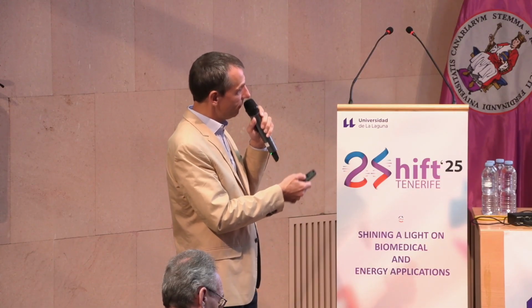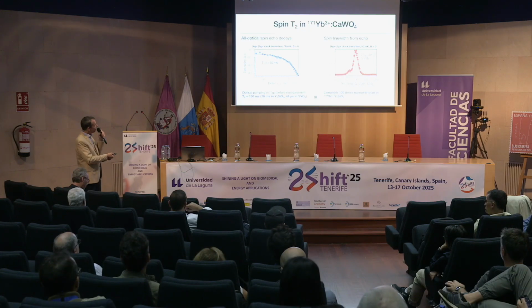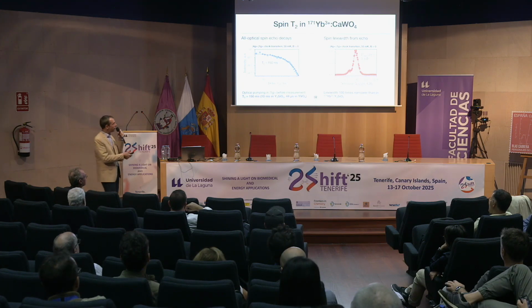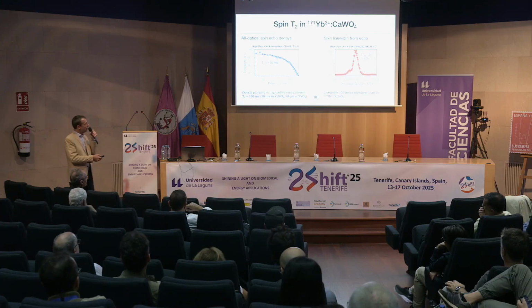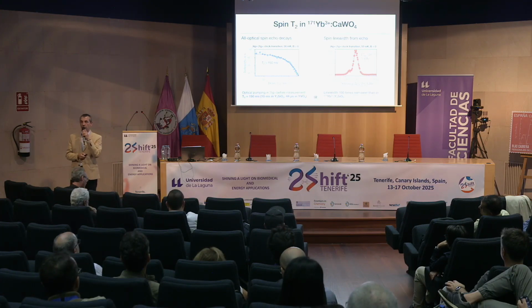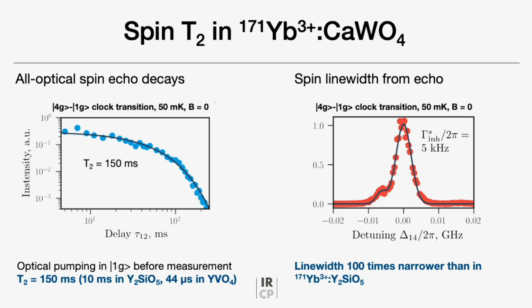Finally, for the spin properties, we also looked at the line widths. And here also we found something which is really outstanding, which is that the transition has only a width of 5 kilohertz. And if you compare this line width with what we measured in ytterbium-171 in yttrium orthosilicate, now we have a decrease in the line width of a factor of 100. And this is a really very significant improvement.